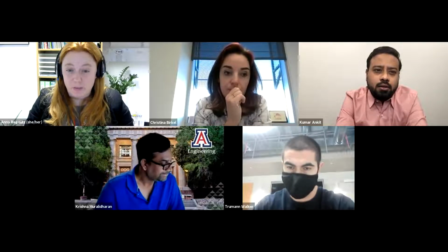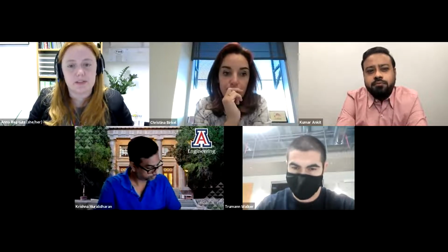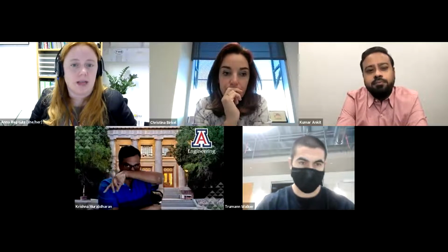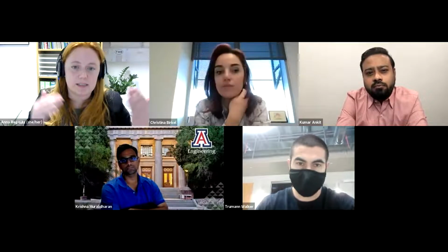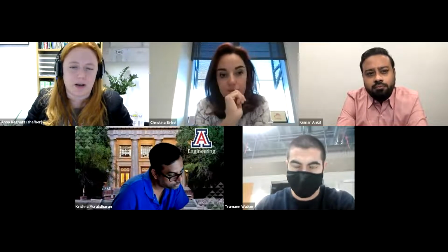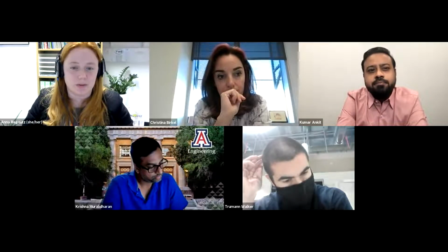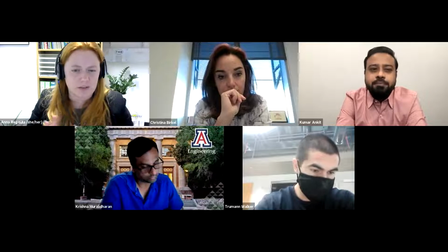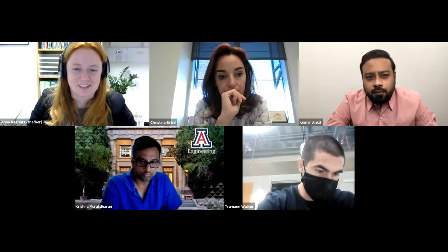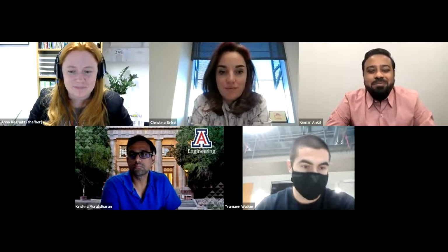I think there are many different ways, right? The example I showed, this titanium tungsten, is also only one example of a diffusion barrier. So I think there are different strategies of how you stop the diffusion, right? Grain boundary decoration is one of them, but designing materials with high defect densities that can capture the copper atoms as they go through would definitely be an alternative. There are also other thoughts of structuring these things, and of course there's also a thickness dependence, or even multi-layer stacks. There are lots of different ways of doing it. The only thing is, you still have to somehow retain your metallization contact. It still has to be an electric contact, otherwise it wouldn't work. So yeah, thank you.